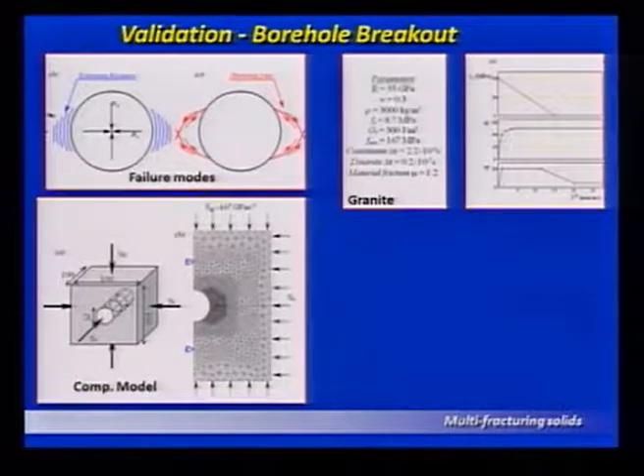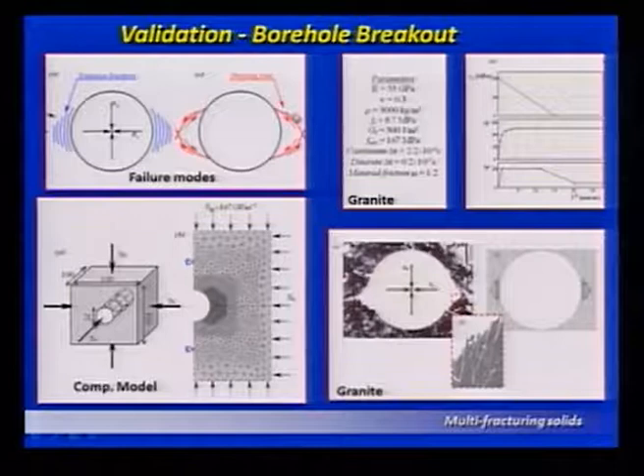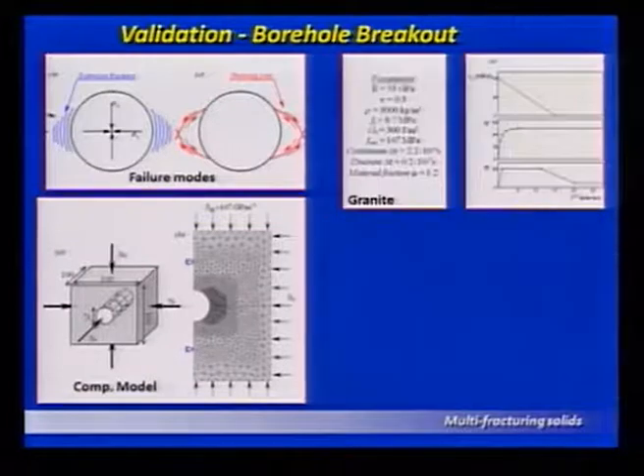This is what is called the standard problem of borehole breakout, where you can take a piece of material, drill a hole through the center, and then apply a series of pressures on it. For our model, the right-hand side shows that the only material parameters you need for these problems are the tensile strength, the fracture energy release rate, compressive strength, and also the parameters that you get from a hydrostatic stress: the cohesion, friction angle, and the dilation angle.